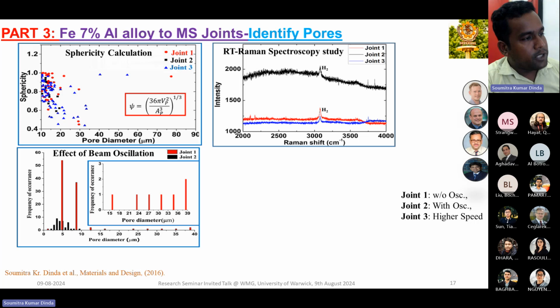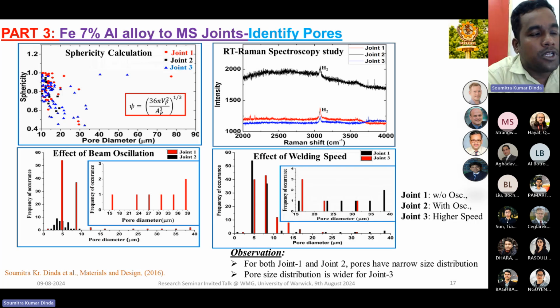And then we do the quantitative study. First, see the effect of beam oscillation. If we compare joint 1 and joint 2, we see the beam oscillation effect. In case of joint 2, we did not find any bigger size pore, that means the pores are very small. In case of welding speed, if you increase the welding speed, that means joint 1 and joint 3, here also the bigger size pore is not visible at high welding speed, suppose more than 30. Only the black one is joint 1. So from the porosity or defect point of view, joint 2 is in the topmost position, then joint 3, and then joint 1.